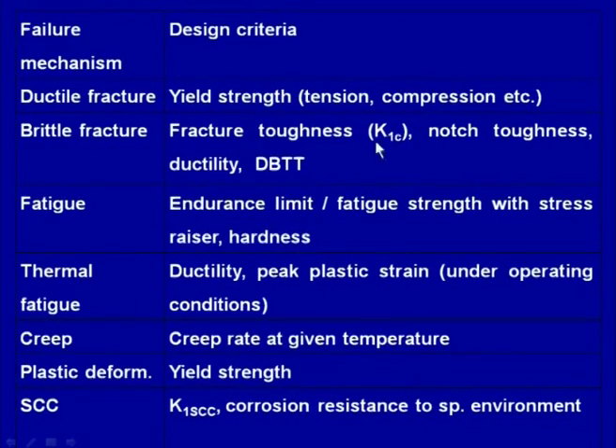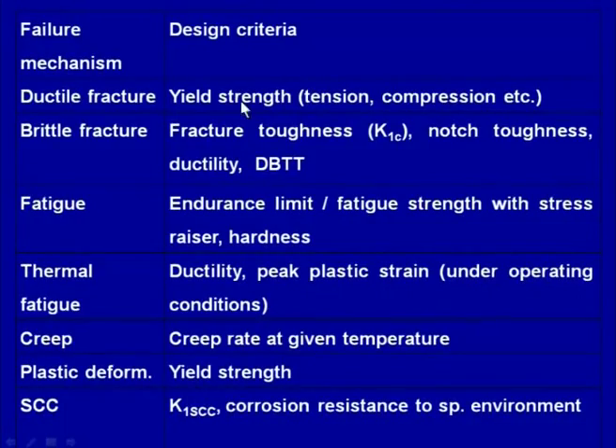This table shows the variety of expected failure mechanisms under which a particular component can fail during the service, and the suitable design criteria. So based on the properties of the material, a suitable material should be selected. For example, if the material is expected to fail by ductile fracture, then the yield strength should be the design criteria, according to the yield strength in tension, compression, shear, depending upon the nature of the load which can act on the component. Then for brittle fracture, if brittle fracture is a possible criteria, then the fracture toughness like K1C, notch toughness, ductility and ductile to brittle transition temperature should be considered.